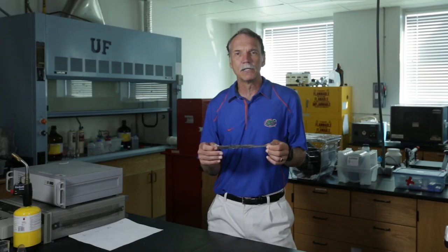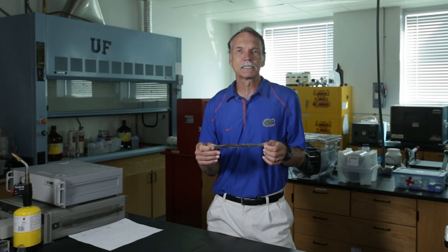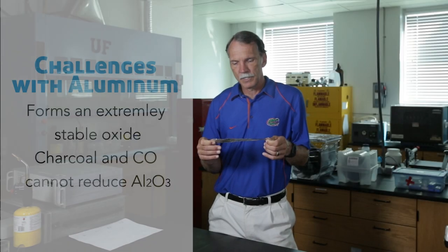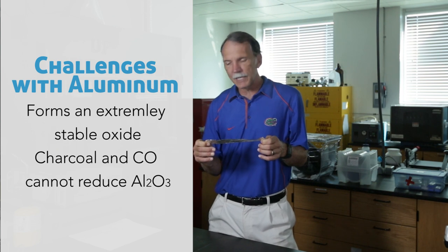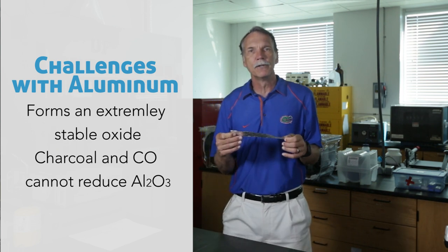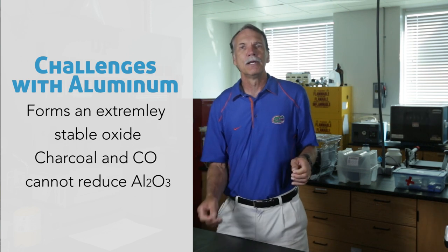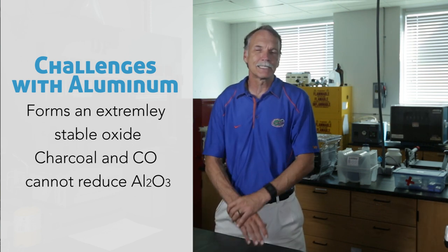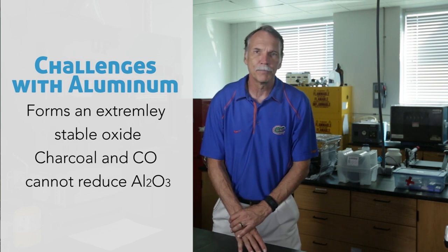In other words, if you look at aluminum, you would think that if something as common as aluminum, it would have been used 3,000 years ago. The challenge with aluminum is that it forms an extremely stable oxide. It forms an aluminum oxide, Al2O3, on the surface. And it turns out that you cannot reduce aluminum oxide using charcoal or carbon monoxide. And that has been the medium in which we've used, the reducing agent we used for the copper and for the iron, et cetera. And so they really didn't know that aluminum was a metal for a long time.